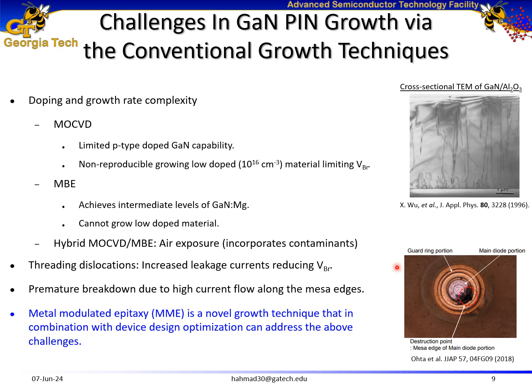There are a few challenges in growing gallium nitride based pin diodes using conventional growth techniques. For example, MOCVD has limited p-type doping, and it is also non-reproducible in growing low-doped material. On the other hand, molecular beam epitaxy achieves intermediate levels of magnesium-doped gallium nitride films, but it cannot grow low-doped material. Hybrid MBE-MOCVD has also been tried, but it suffers from incorporation of contaminants.